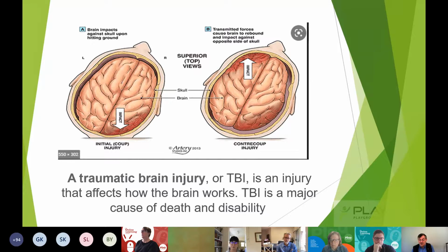But it could only have a critical fall height of 500 millimeters because the head will punch through the 20 mils and hit the concrete below, and you'll end up with a sharp impact, a very narrow time impact. And you can have a hard surface that feels like concrete under your foot, but it's 100 millimeters thick and gives you a 3 meter critical fall height. I've walked on a few of these and gone, oh, this can't be a soft fall surface. It's so hard, I can't even jump up and down. It doesn't move at all. But as soon as you drop the head, it tells you a different story.